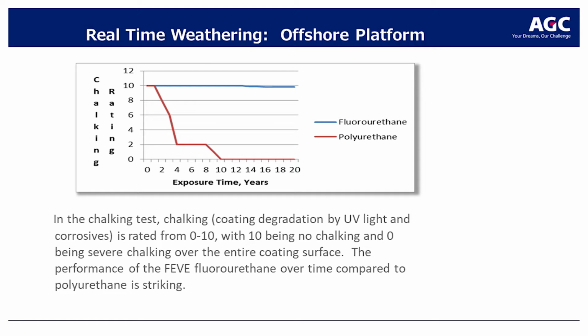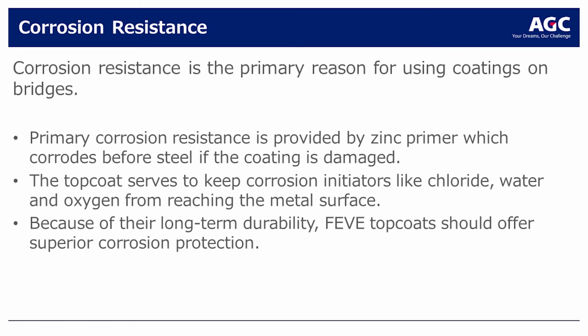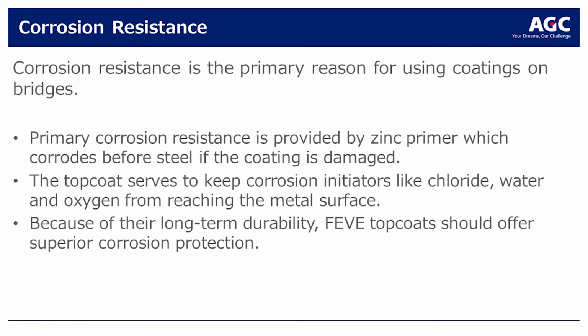The reason people use coatings on bridges is really for corrosion resistance. Appearance is nice. You can have bright colors on bridges. There's a call for that. In most cases, people are using a 3-coat system consisting of a zinc primer, usually an epoxy middle coat, and then a urethane or polyurethane top coat. And there are variations on that. You can do 2-coat systems and things like that. But primary corrosion resistance in those systems is provided by the zinc primer.